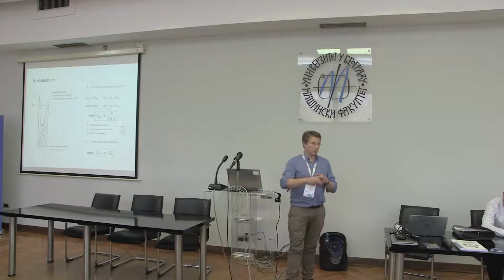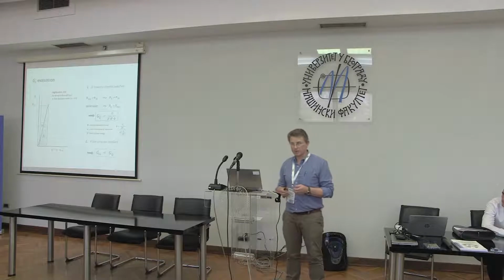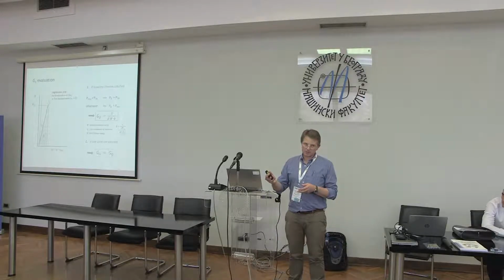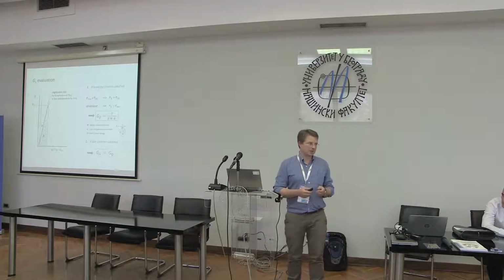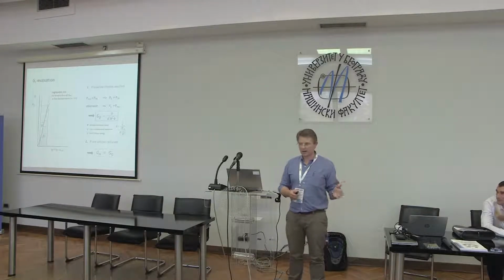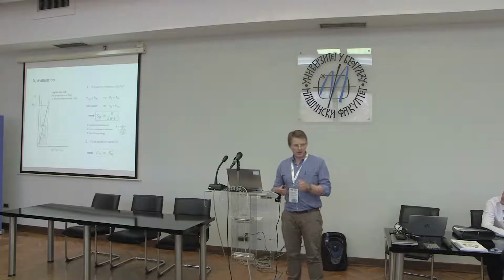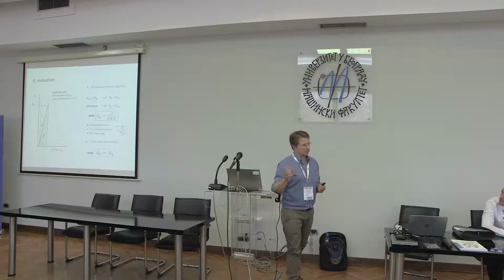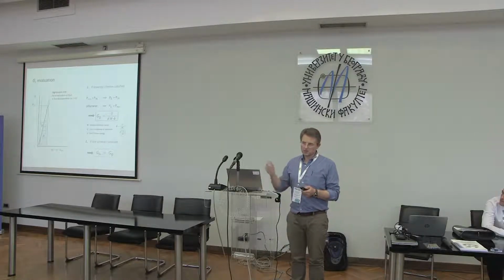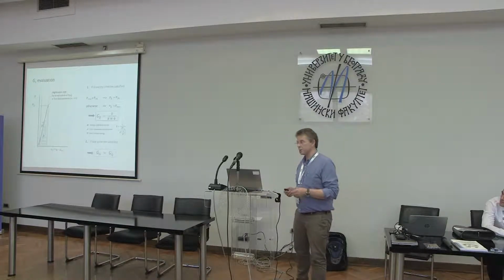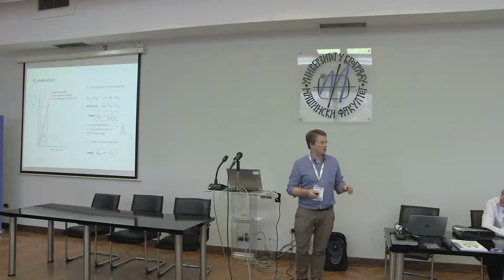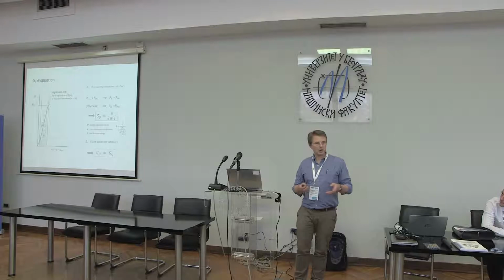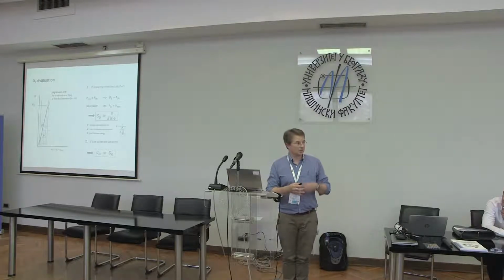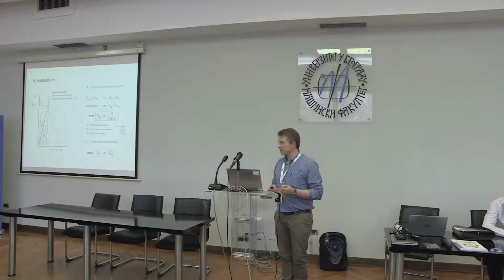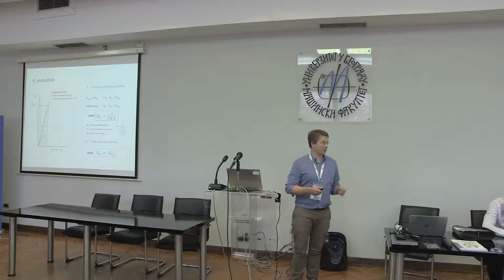What the people working on metal cutting originally said was that the fracture toughness of metal is low compared to the energy dissipated plastically during the process, and therefore we'll ignore the fracture toughness term. Tony Atkins, relatively recently in the UK, commented that the flaw in that technique was that the fracture toughness they were considering was not the true fracture toughness, but was the surface work. It was more akin to the surface energy rather than the fracture toughness. And of course, we all know that the fracture toughness is different from the surface energy because of what is being dissipated plastically at the crack tip. So it was an incorrect assumption just to ignore fracture toughness.